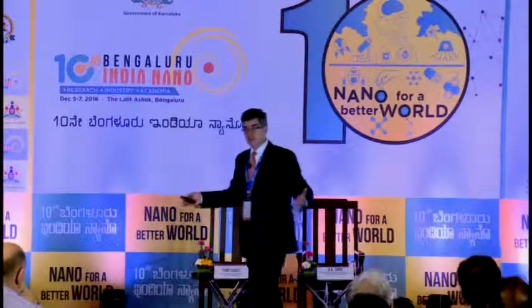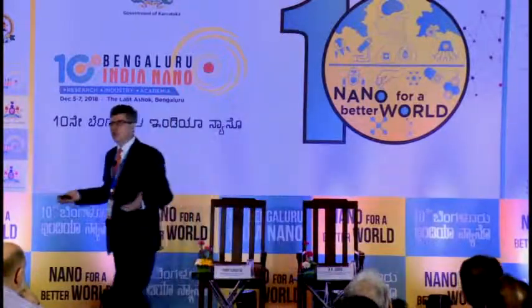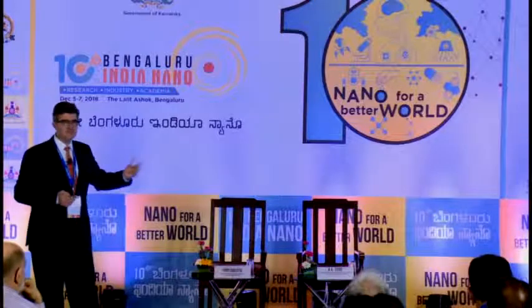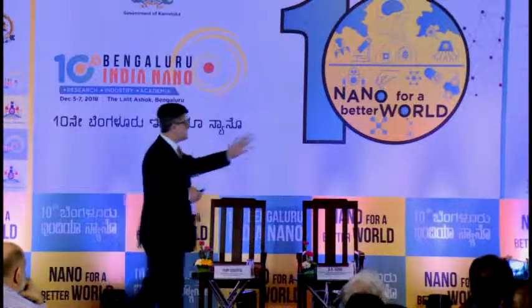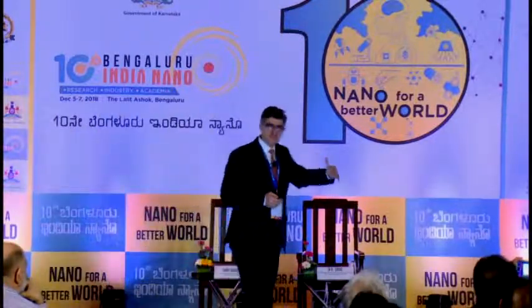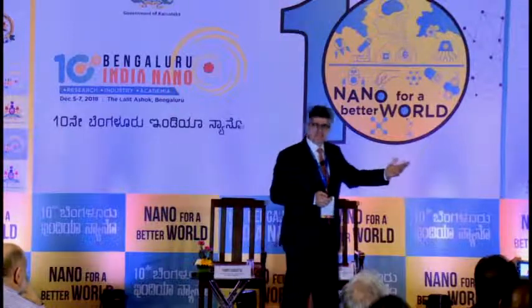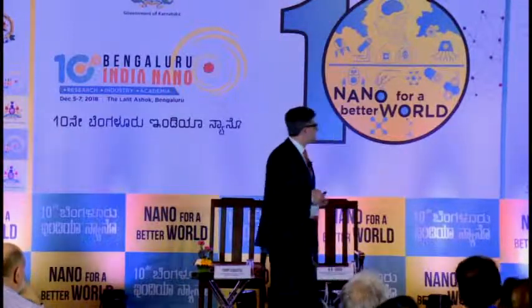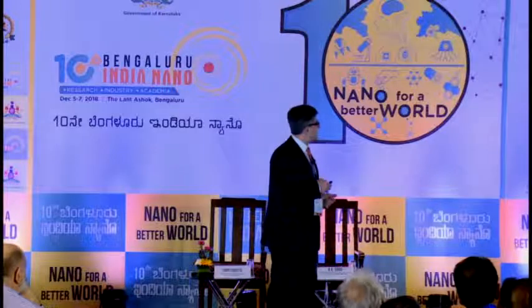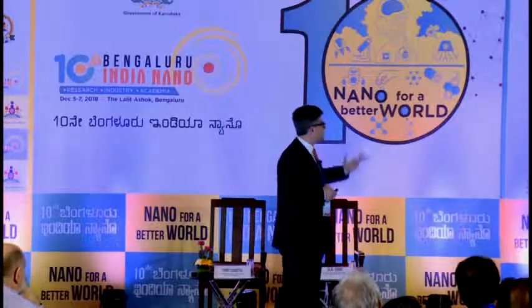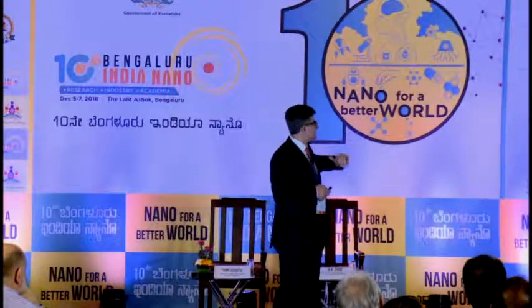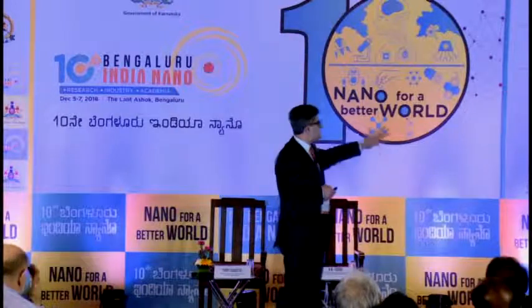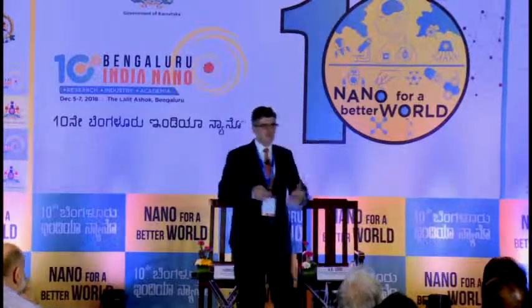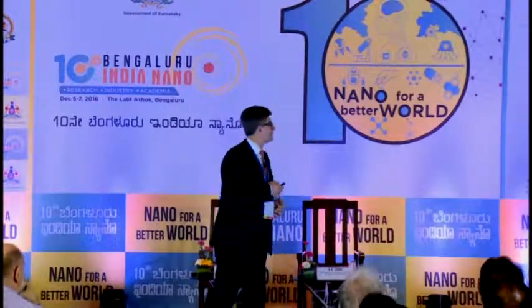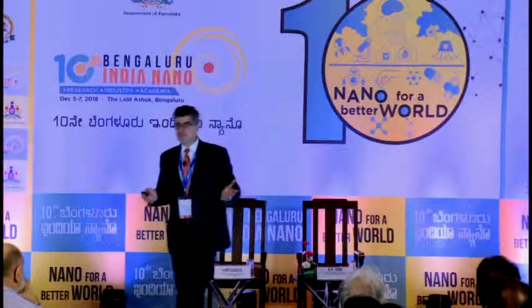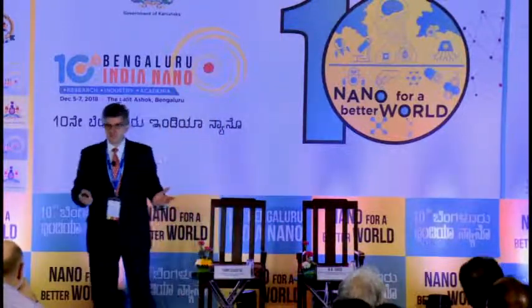Here, you can use them as a conducting additive to other materials. For example, sintering with zinc oxide ceramics, it suppresses grain growth and at the same time gives conductivity with just 1% of additive. As a result, for example, it's possible to increase both hardness and Young's modulus of zinc oxide ceramics, and the power factor in thermoelectric applications. We can also make a variety of films and composite materials.